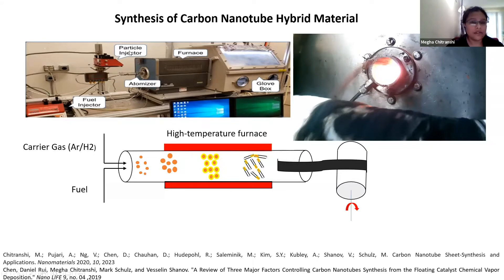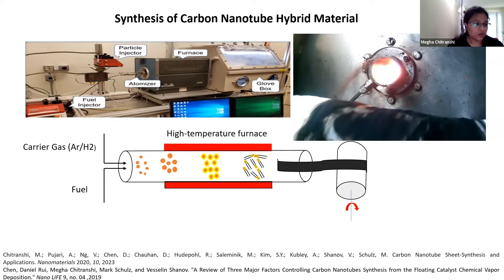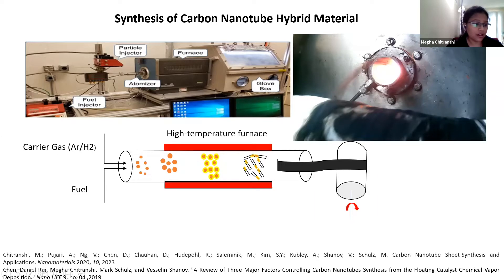If we want to integrate nanoparticles into our CNT synthesis, there is a particle injector that is customizable — you can adjust it according to which particles you want to inject and at what temperature. As the fuel enters the atomizer, it is broken into micron-size droplets. The gases are among various variables that determine the state of the sock, and the process must be carefully tuned to prevent breaking of the sock. In the first part of the reactor, catalyst nucleates from iron atoms under diffusion and agglomerates. The CNT growth region is located in the middle part of the furnace, which is mainly the high-temperature zone, where hydrocarbon decomposes into free carbon atoms that combine with the catalyst to produce CNTs.